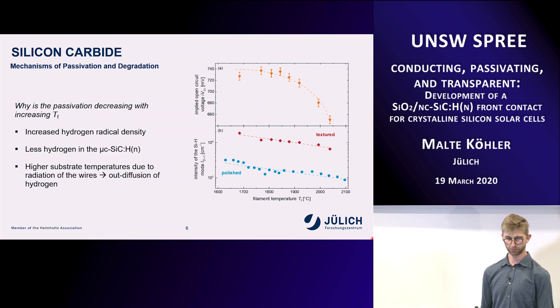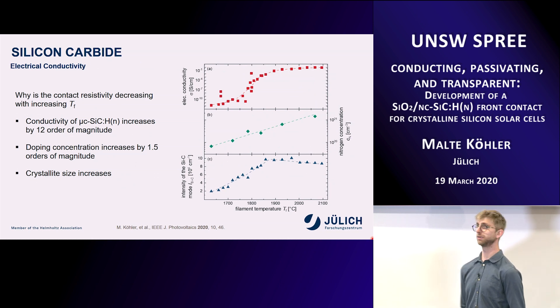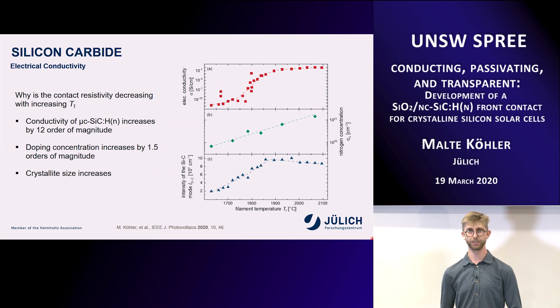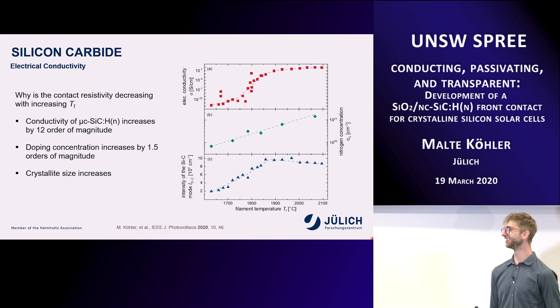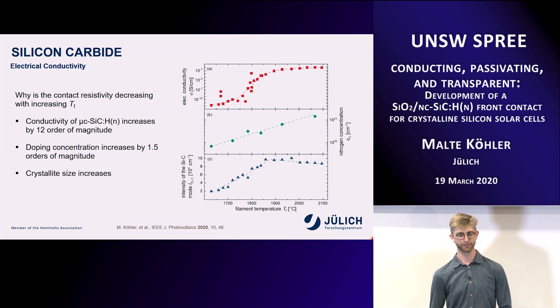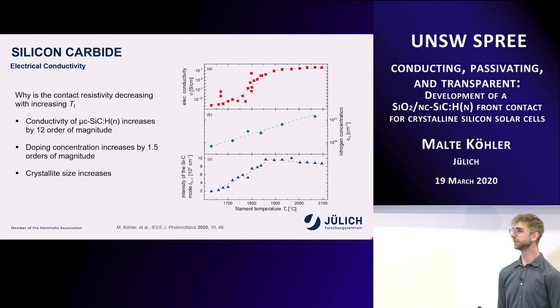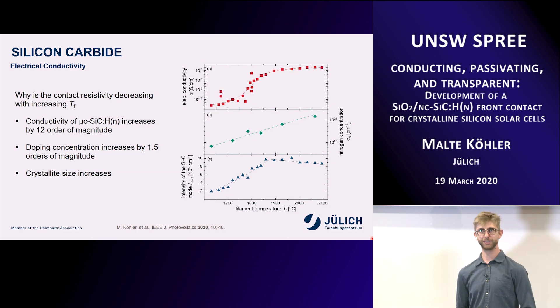The second question was: why does contact resistivity go down with increased filament temperature? The answer is interesting. In the beginning, electrical conductivity increases by about 12 orders of magnitude across this filament temperature range. We didn't change anything else — just tuned the filament temperature. That's why internally we sometimes call it the magic material. We tried to find out why, and we thought the nitrogen concentration might be increasing even though the flow was constant. Indeed the nitrogen concentration increased, but only by about 1.5 orders of magnitude, so there is still room for other explanations.